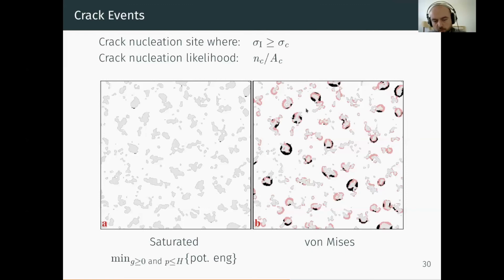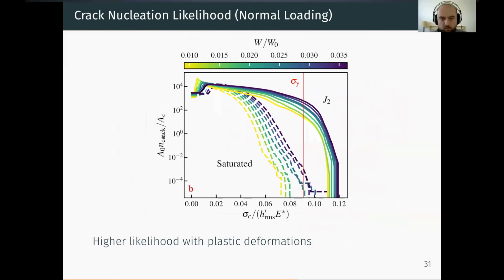So what I do to compute this probability that a contact will nucleate a crack is I count how many crack nucleation sites I have in my total system, and I divide it by the true contact area. This quantity turns out to be proportional to the probability of forming a crack. So this is what I show in this plot. This is the crack nucleation likelihood. This is the critical stress, and here is the normal load, which varies the colors here. So basically each curve corresponds to a different normal load.